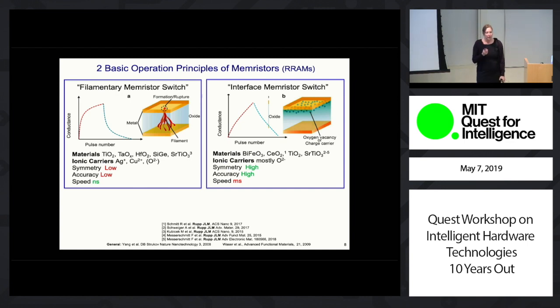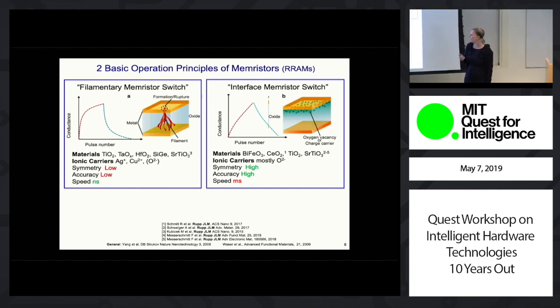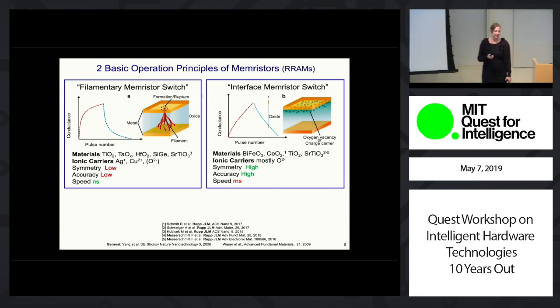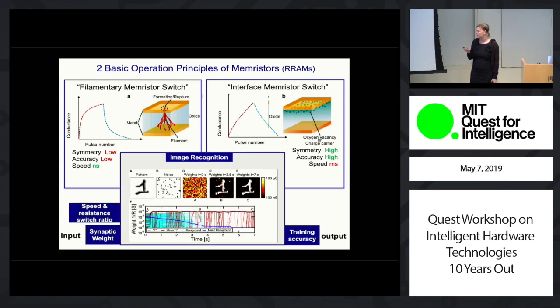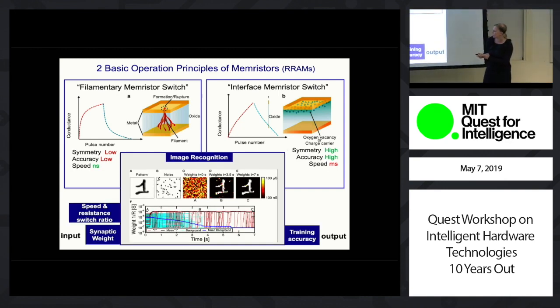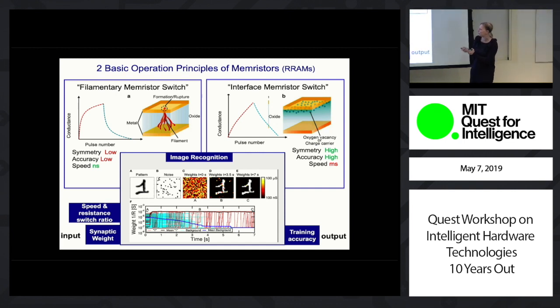Okay? So you are in a constant dilemma with memristors. I call it the memristor dilemma. You either have a fast speed but a low symmetry and low accuracy, or you have a low speed and a high symmetry and accuracy in the memristor, depending on what you pick. So what's the impact of that? The impact is later in image recognition, which is one part of what you want to use these deep neural networks for, as Vivian just pointed out. If you have a pattern, then the ratio between the resistances that you can access and the symmetry will define the synaptic weight.